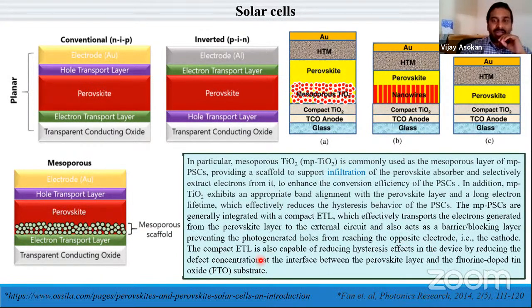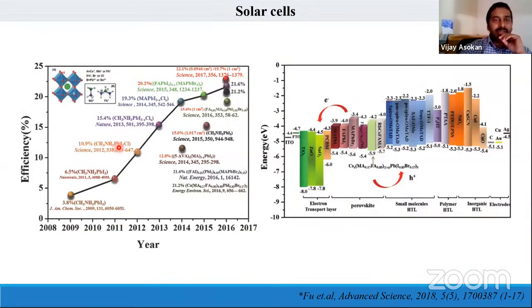So the compact ETL is also capable of reducing the hysteresis effect in the devices by reducing the defect concentration at the interface between the perovskite layer and the fluorine doped tin oxide. That's a transparent conductive oxide layer. Yeah, these are the materials within the perovskite devices.